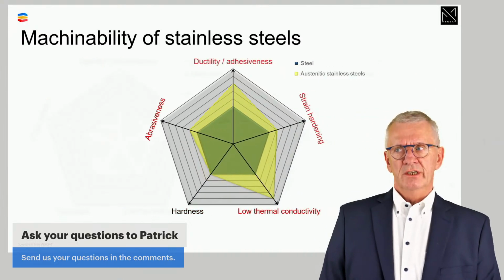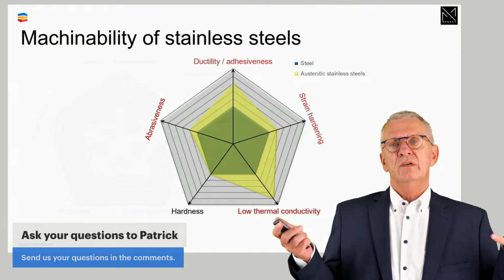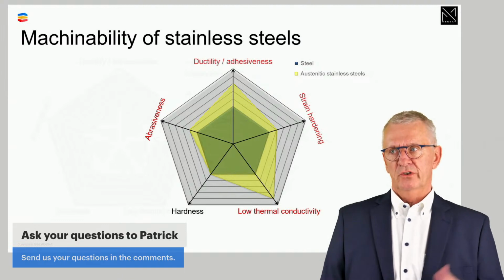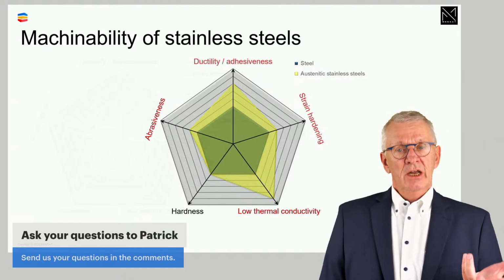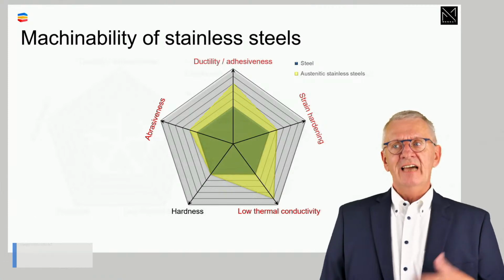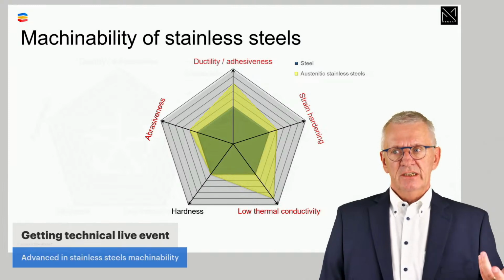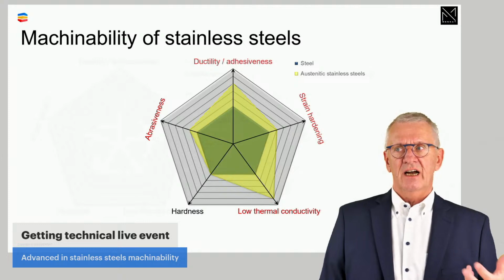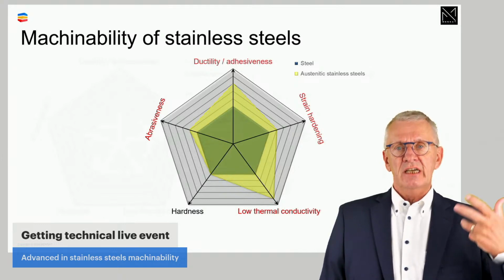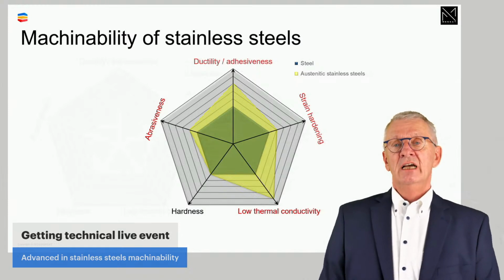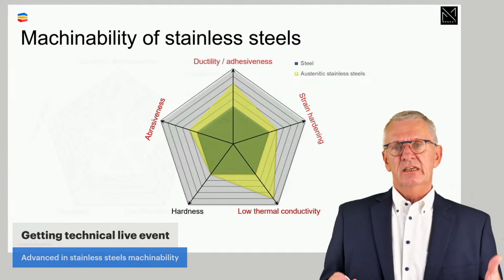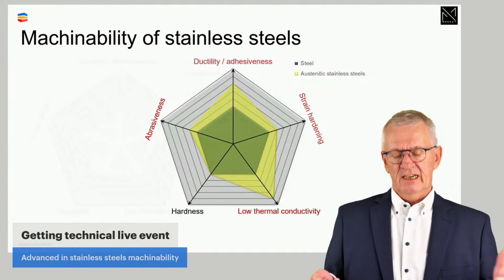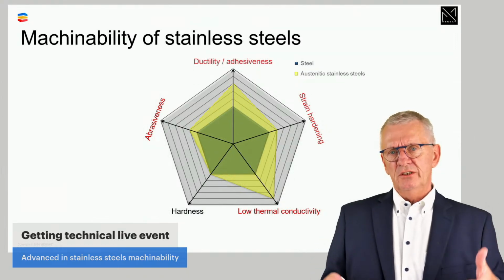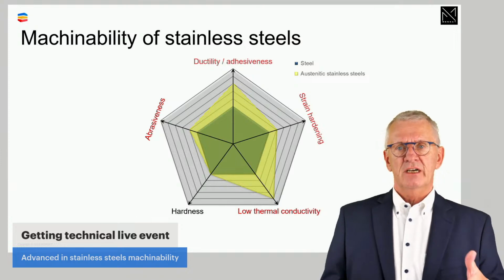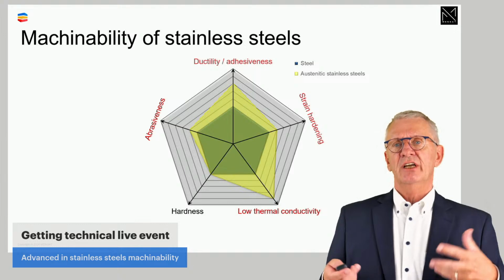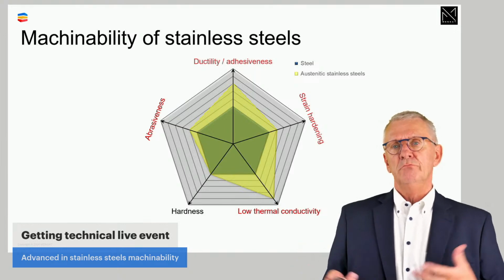If we look at austenitic stainless steel, and I put this one in the middle because it's the one we find mostly in industry, in the workshops today. Here we see, with the exception of hardness, that compared to traditional steel, everything is more present. It shows higher abrasiveness, higher ductility, higher adhesiveness, higher strain hardening, and seriously lower thermal conductivity compared to steel. So machining austenitic stainless steel demands, and that was the challenge back with the project we had a long time ago, tools specifically designed for a different type of environment. It demands cutting conditions which are selected in line with what the cutting edges will be submitted to.